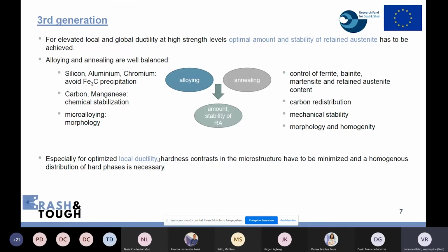We use microalloying to get a particular morphology to stabilize the austenite. And during the annealing steps, we control the ferrite, the bainite, the martensite, and the content of retained austenite. We control the carbon redistribution. We regulate the mechanical stability of the retained austenite, and we generate a particular morphology and a good homogeneity of the retained austenite and the other phases in the microstructure. Well, especially for the optimized local ductility of these third generation grades, hardness contrasts in the microstructure have to be minimized, and a homogeneous distribution of hard phases is necessary.